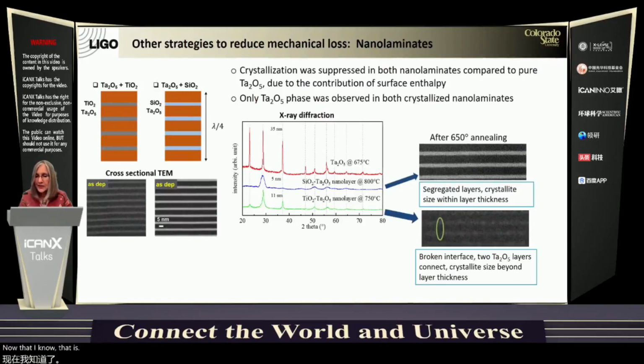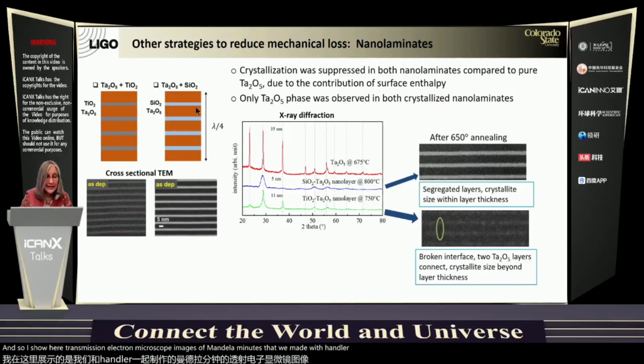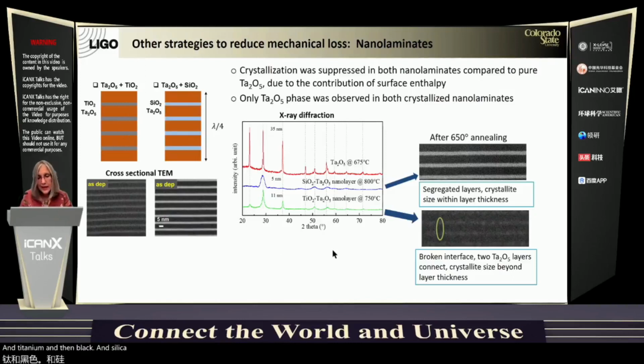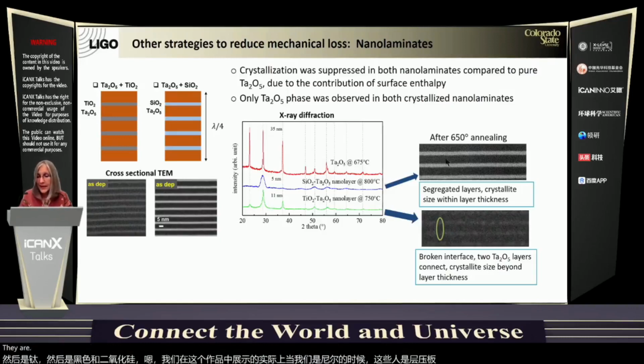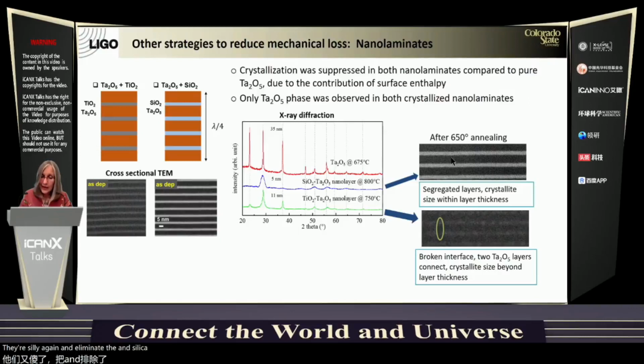Now, there are other strategies that are being investigated to reduce mechanical loss in amorphous oxides, and making nanolaminates is one of them. And so I show here transmission electron microscope images of nanolaminates that we made with tantala and titania and tantala and silica. And what we showed in this work is that when we anneal these nanolaminates, the silica tantala nanolaminate remains intact, but the titania tantala nanolaminate instead has its interfaces break, showing that there is diffusion of tantala and titania.